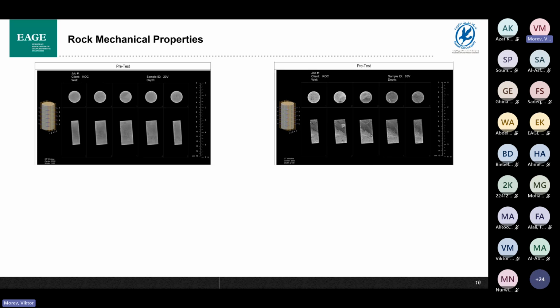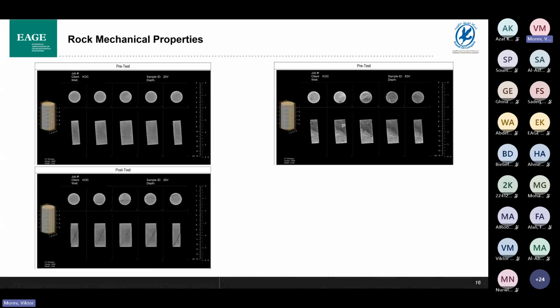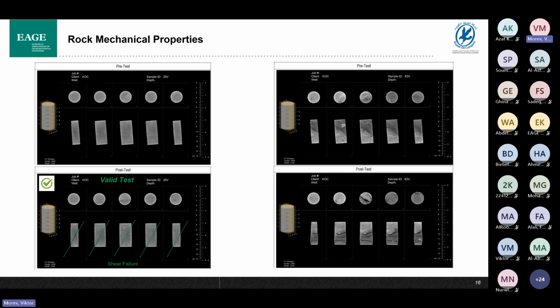On the left side, the sample develops a clear shear failure plane. This is the type of failure we are looking for, and this can be used to support our wellbore stability calculations. On the right side, we see a different non-shear failure mechanism, pore collapse or compaction, and we consider this test as not valid, and we will treat the results differently. This is one of the examples of the quality check of results of the geomechanical lab studies.